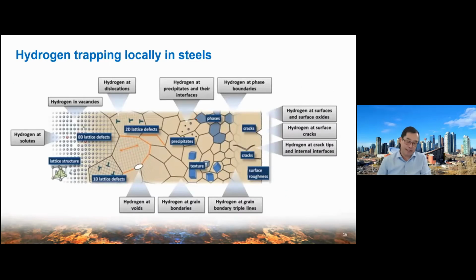Unfortunately, all steels must include different types of metallurgical features. These features can trap hydrogen and make the hydrogen locally concentrated in this area. For example, all steels will include lots of dislocations. This is a typical linear defect in the steel. The dislocation density can go up significantly if the steel is under stress.